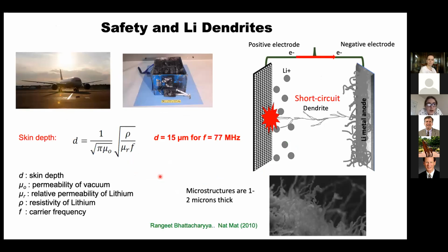So I'll just tell you one more story now about safety. This is the picture of the poor Dreamliner that was grounded a number of years ago. At least one thought behind what was going on was that there were dendrites that were forming and catching fire. The reason you don't use a lithium metal anode, you use graphite instead, is that instead of forming nice smooth deposits on lithium metal, you can form these dendritic structures. And then if they short circuit, then you have problems and fires.